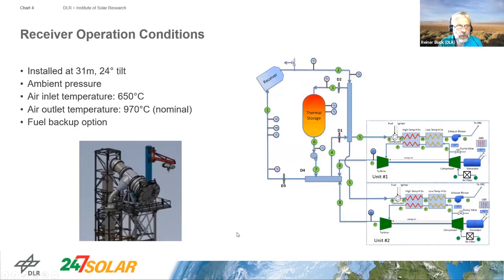Just to give you an indication of the operating conditions, the receiver in a typical layout is installed at a height of something like 31 meters, tilted by, for example, 24 degrees. And it's operating at ambient pressure with an air inlet temperature of 650 centigrade. This is defined by the gas turbine cycle, the exit temperature of the recuperator. And it's designed for an air outlet temperature of 970 centigrade. And of course, the overall system has a fuel backup option, and it's also designed to operate with the thermal storage.